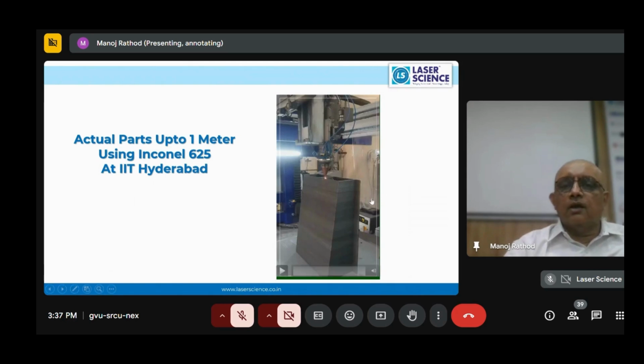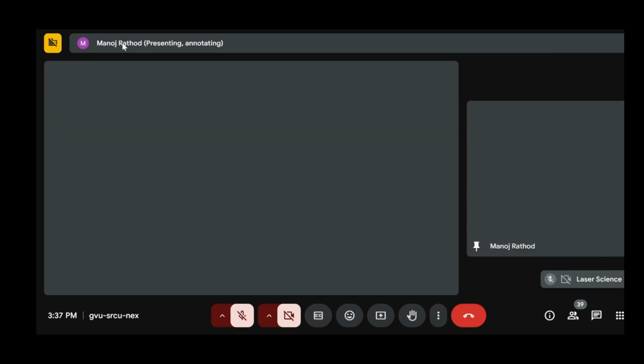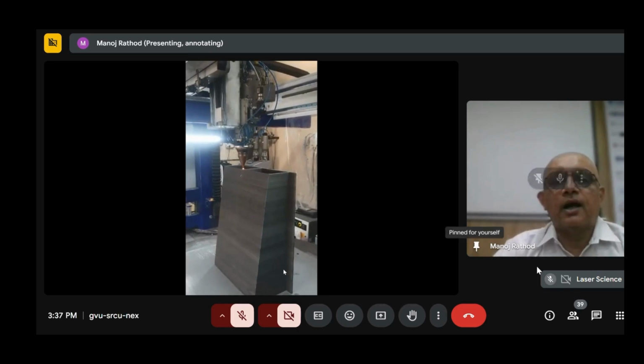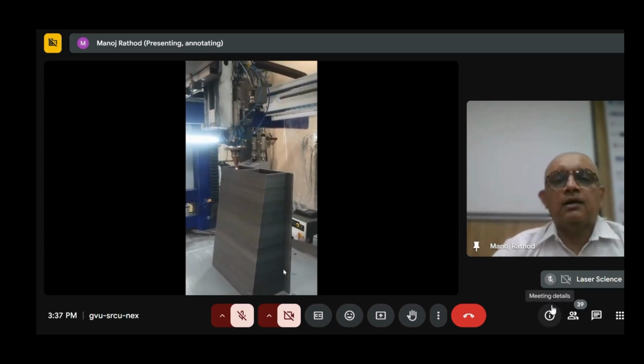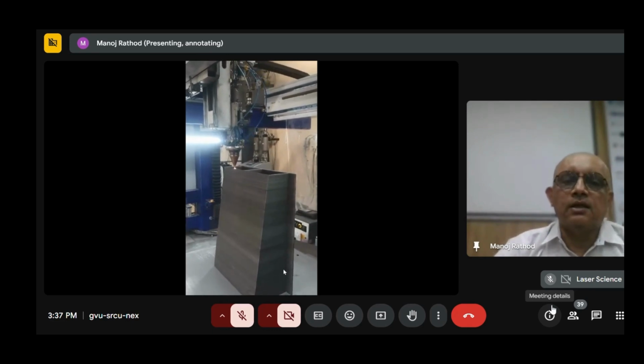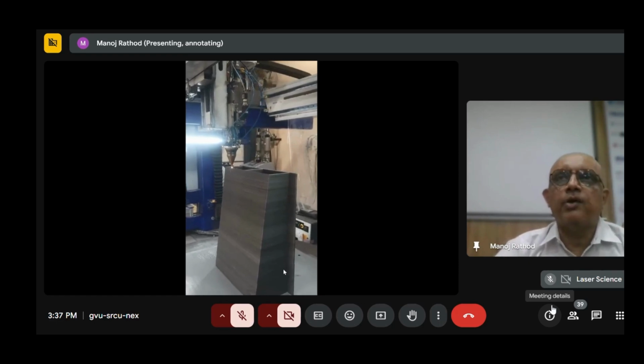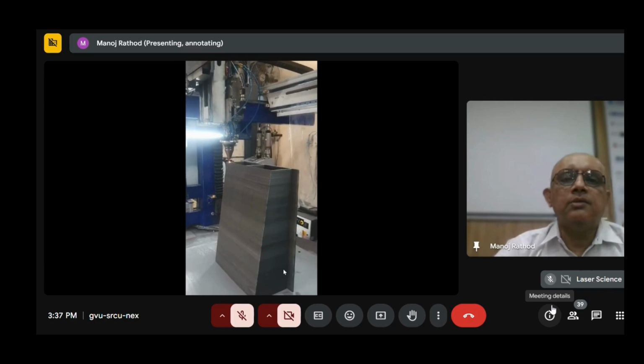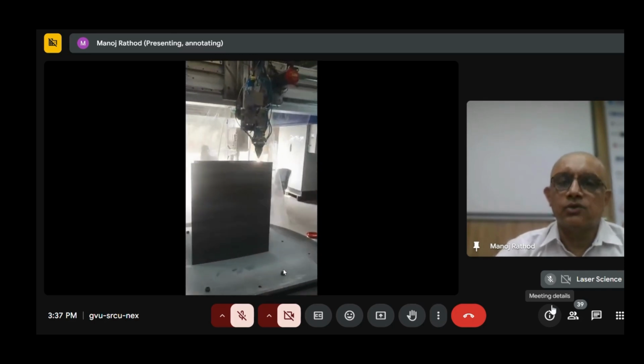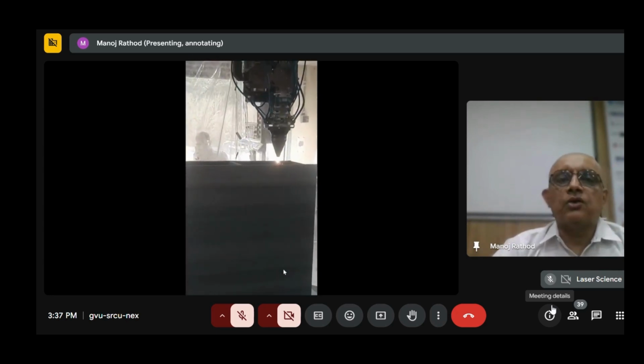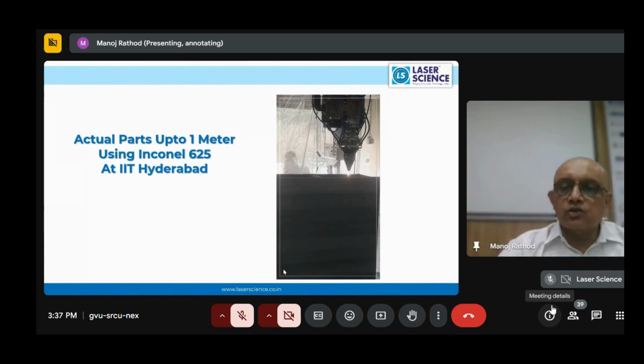When we built this system, we never imagined that it could also print a very big part of this size. And when we saw this actually printed, I am glad to run this video, with IIT Hyderabad's help, where you can see how nicely almost 1 meter of Inconel 625 powder has been built. And sometimes these systems are running for more than 10 days also. So continuous operation of this laser has been ensured by us while we were designing this system.